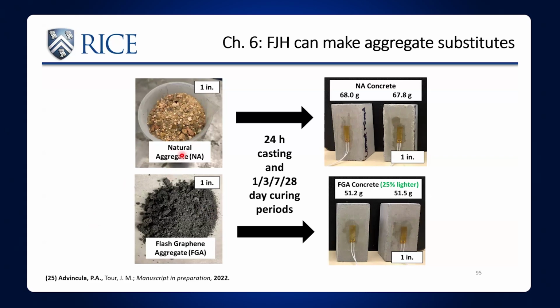So what he did is he analyzed this. He says, okay, how much of it is sand? How much of it is 1 millimeter diameter rocks, 2 millimeter? And then he ground up his flash graphene into those same size patterns. All right, so you can sieve it out. You have sieves. This is something you can easily automate, but he was just using these hand sieves. And then he put it in the concrete, made concrete out of it instead of using natural aggregate.